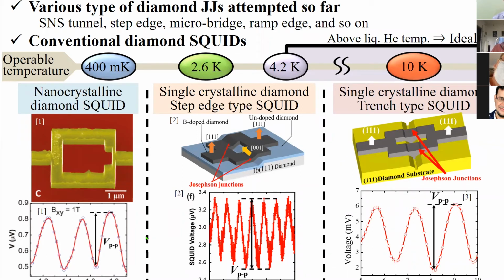Before our work, the pioneers made a SQUID using nanocrystalline diamond. Nanocrystalline diamond is diamond, but it has small crystals. It shows a very nice SQUID, even at low temperature. They first published this in ACS Nano in 2011. The Josephson junctions they made for the SQUID are formed by a lot of crystal boundaries - there are many boundaries, I think, so we don't know exactly where the Josephson junction is. It's multiple junctions, but anyway they show a really good SQUID. You can see the oscillations here as a function of the magnetic field.